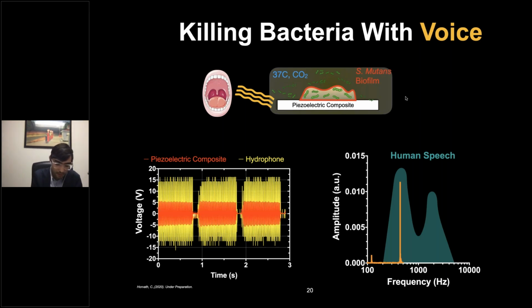So what you see here in yellow is the signal captured by a good, calibrated, highly effective hydrophone, and the ones measured by our piezoelectric composite are shown in red, which is great. It's very comparable. We saw a decrease in the intensity of the voltage, but that's expected because our composite is not as effective—the power translation between the acoustic signal and the electrical signal is not as effective as a full 100% piezoceramic.